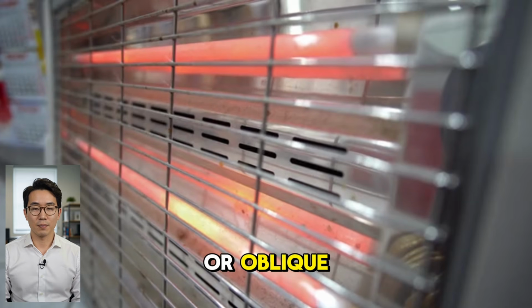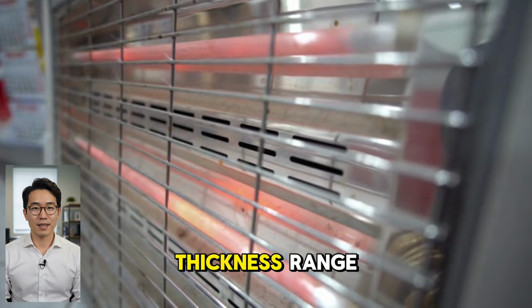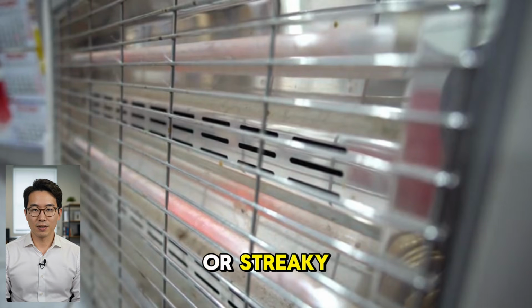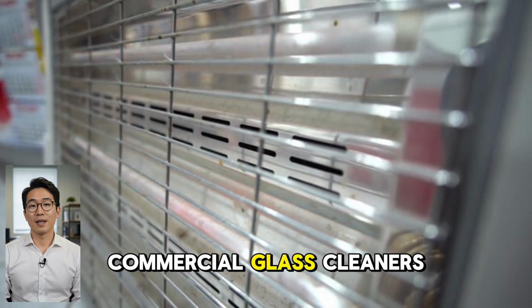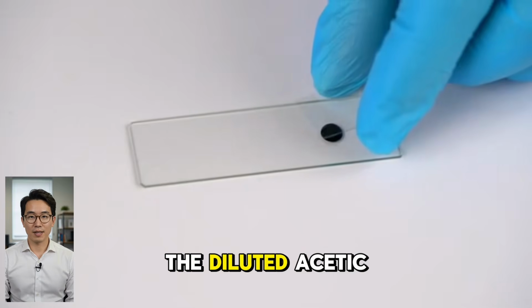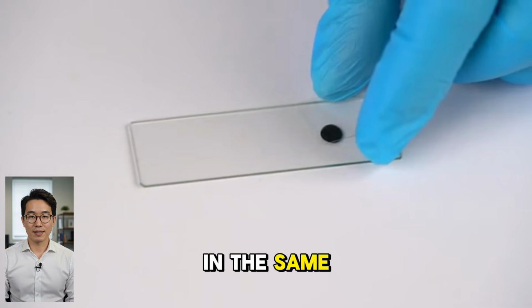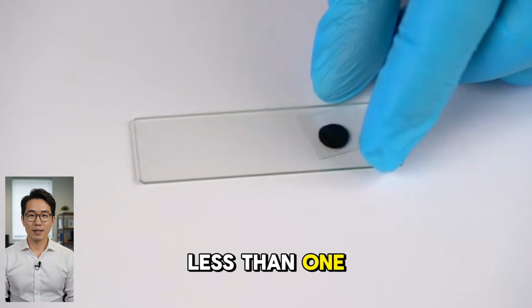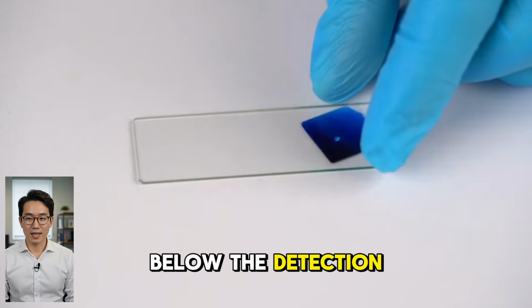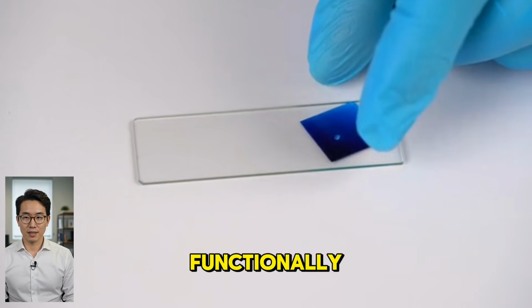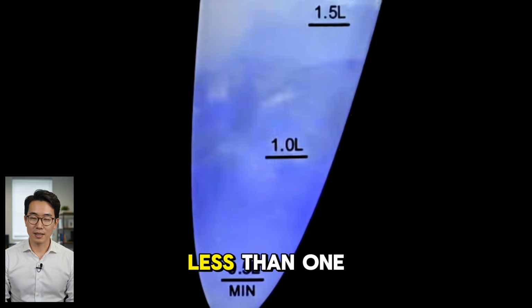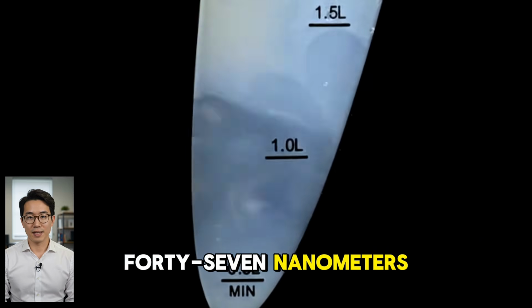Under direct sunlight or oblique artificial lighting, films in this thickness range create the hazy or streaky appearance that users of commercial glass cleaners report universally. The diluted acetic acid solution tested in the same study left a residue film of less than 1 nanometer after drying, below the detection threshold of the measurement technique and functionally equivalent to zero residue. Less than 1 nanometer versus up to 47 nanometers.